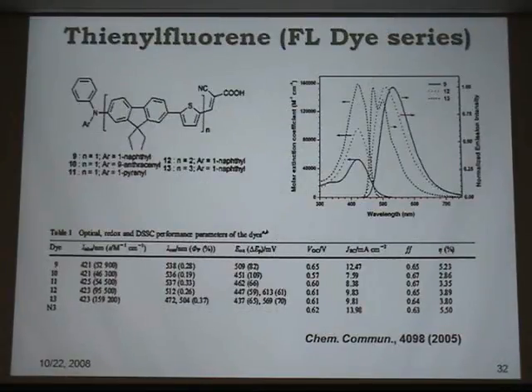Now let's move to another dye, the FL dye. If the chain length is very short, n equal to 1, we have achieved an efficiency of 5.23% as compared to N3 at 5.50%. Remember, when we published this work, this was in 2005, we only used about 2 layers of titanium dioxide, which is around 12 micrometers.